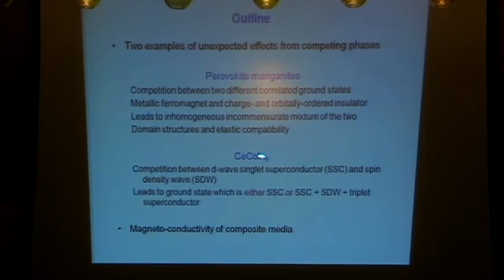But nonetheless, there's some cohabitation and proximity between the singlet superconductor phase and the spin density wave phase. And it turns out that this system can be manipulated by a magnetic field to generate a state which is either this or something which is actually a mixture of three phases, namely singlet superconductor and spin density wave and a triplet superconductor, and they all come together.